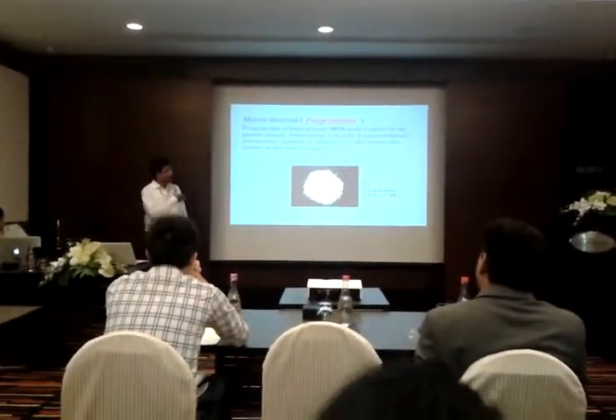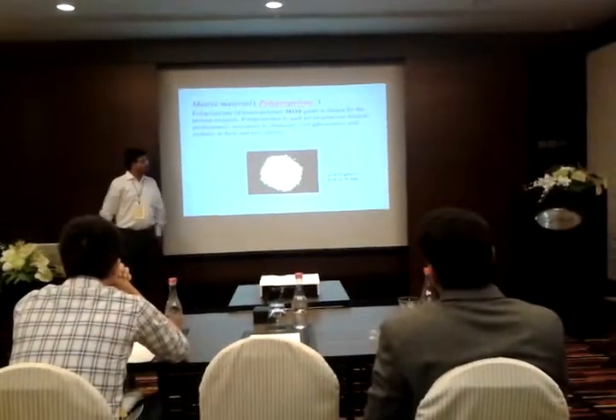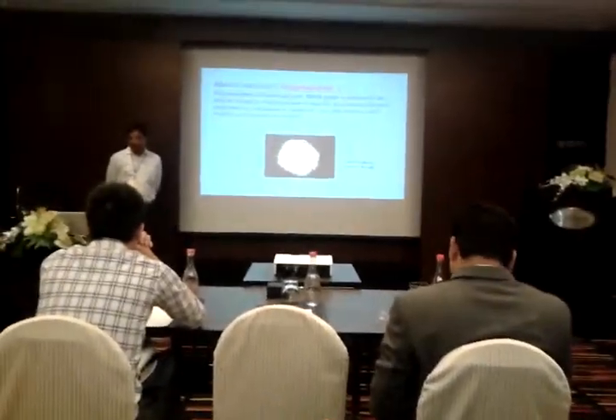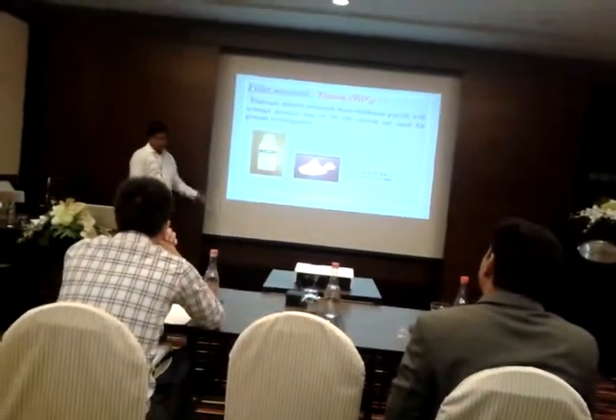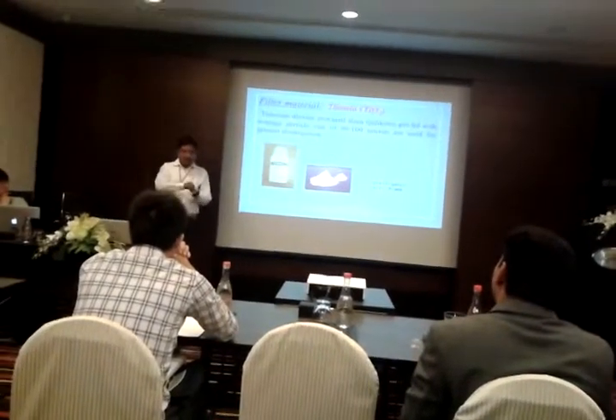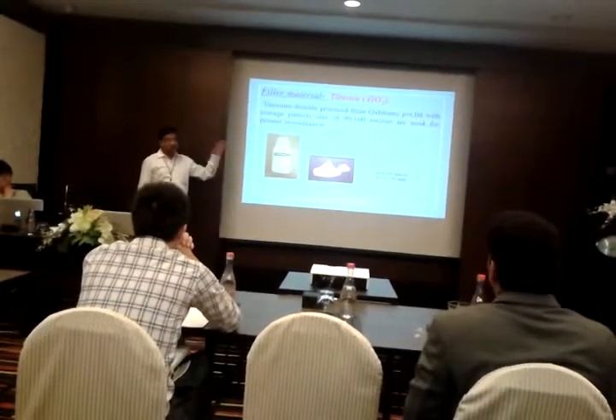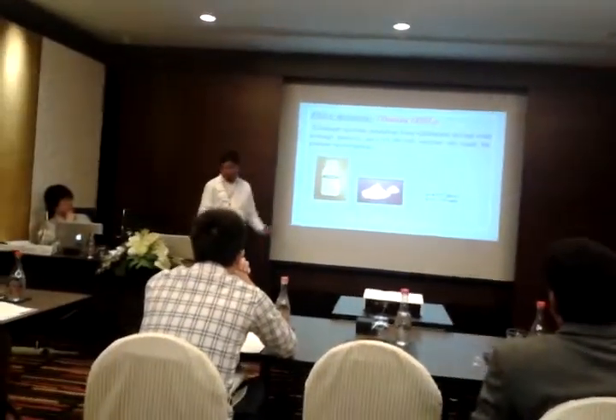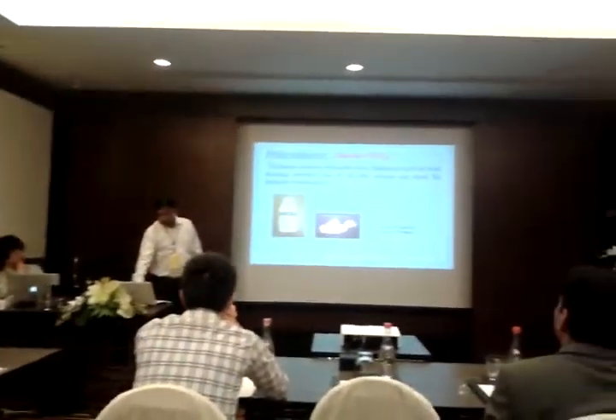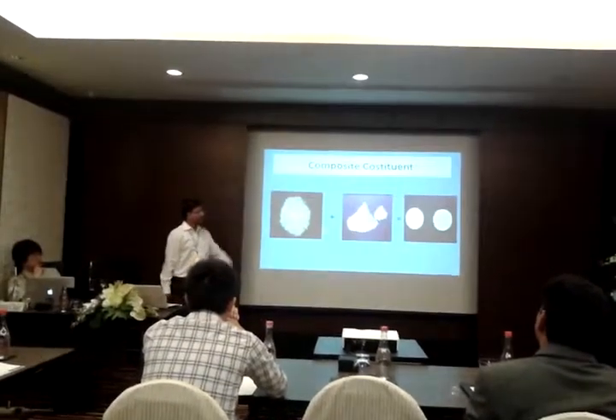This is the polypropylene matrix material in granule form. Its thermal conductivity is very low — 0.11 — and its density is less than 1 gram per cc. It has very good mechanical performance, is cost effective, and has high resistance to chemicals. The filler material I am adding is titania, which has a thermal conductivity 100 times higher than that of polypropylene — 11.7, compared to 0.11. So I am adding titanium oxide into the polypropylene and getting disc-shaped composites, so that we can measure the thermal conductivity.